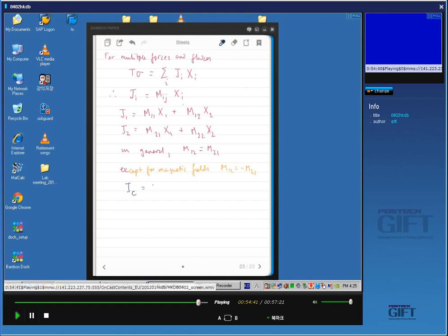and I'm going to assume Fick's ordinary law of diffusion here, the diffusion coefficient of carbon times the gradient of carbon, okay, plus a cross term times the gradient of manganese. So the flux of carbon will not just depend on the gradient of carbon, but also on the gradient of manganese. And this is called a cross diffusion coefficient. That means the dependence of the diffusion of carbon on the gradient of manganese. So if I have an alloy which contains segregation of manganese, okay, so there's a different manganese concentration here from here, and I start with a uniform concentration of carbon, the carbon will redistribute, even though there was no original gradient of carbon. Yeah? So the carbon will migrate.